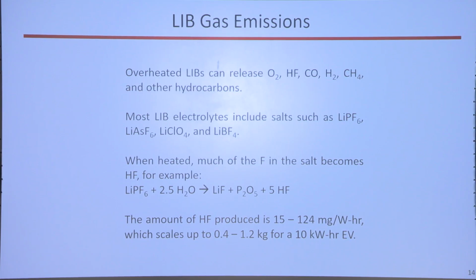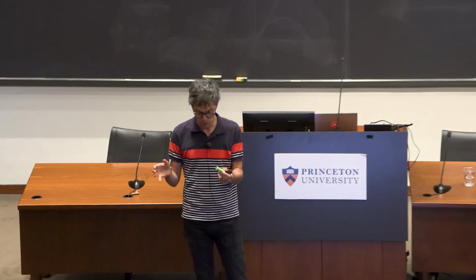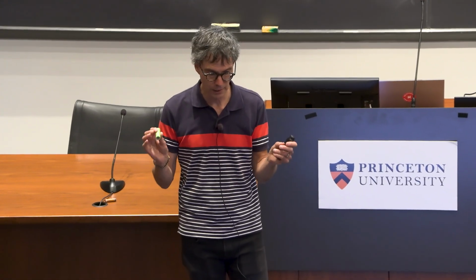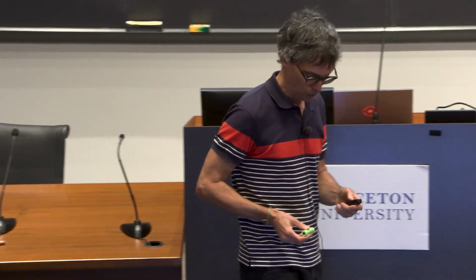And when heated in these salts, most of the F becomes HF. We saw that yesterday, that HF is very toxic. And finally, if you burn an entire electric vehicle, you can expect to produce about a kilogram of hydrofluoric HF. So nothing good comes out of a lithium-ion battery fire. We do some of these experiments in our department, and we're so careful that the vent is working well, none of the gas comes into the room. But even after it's burned and it's cool, you have these toxic battery cases to get rid of, and it's difficult working with these.